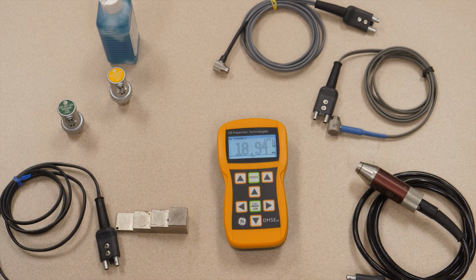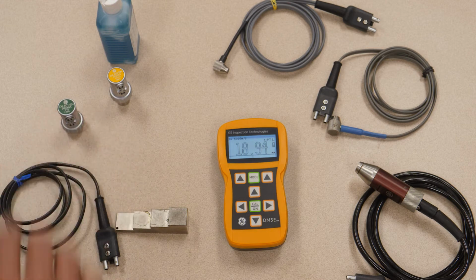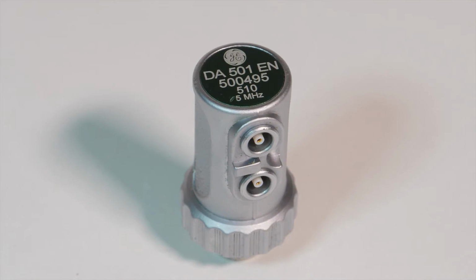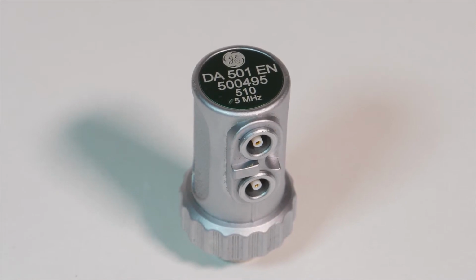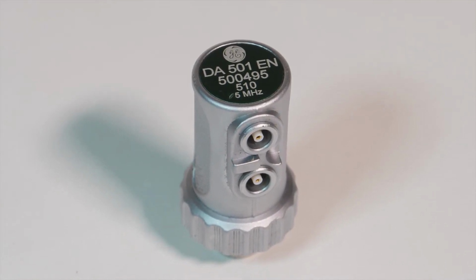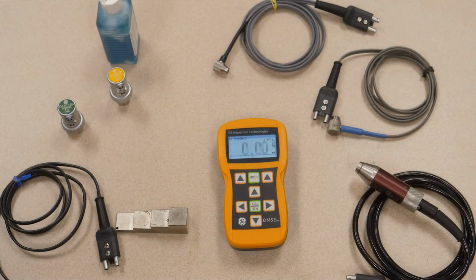Shown with the instrument here are some of the most common probes. The DA501 is probably the most commonly used probe with the DMS E. It is a 5 megahertz general purpose probe, has a measurement range of about 1 millimeter to 200 millimeters, 40 thousandths of an inch to 8 inches.